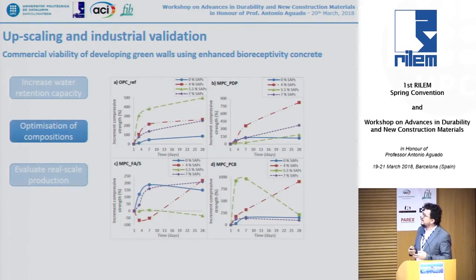We also made an optimization of the compositions in order to use non-laboratory products. We evaluated the use of fly ash in order to reduce the content of magnesium phosphate cement, and also the use of an industrial magnesium byproduct in order to also reduce the cost of this material. But the mechanical results compared to the OPC reference were not so good, so we have to rely on the use of normal dosages.